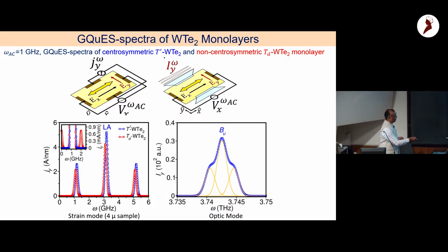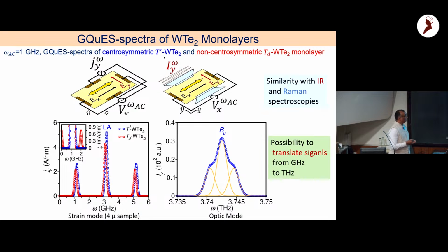For optical phonon, you will see there is a central peak which is associated with the frequency of the phonon, and then two side peaks, and the difference between these two frequencies is exactly 2 times the applied AC voltage. Yeah? The beauty of this is it's similar to IR as well as similar to Raman. You have Stokes, anti-Stokes, and the central peak as well, which is the vibrational peak. More than that, you also have a possibility to translate signal from gigahertz frequencies to terahertz frequencies. So frequency modulation technology can be developed using these ideas as well.